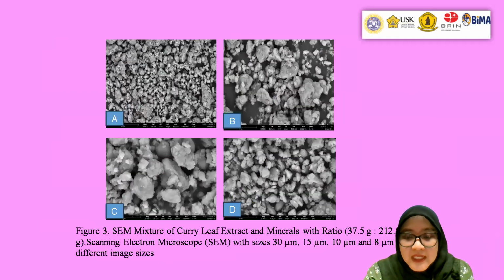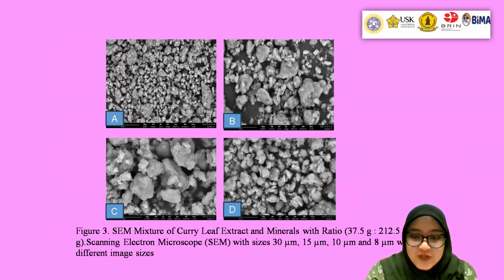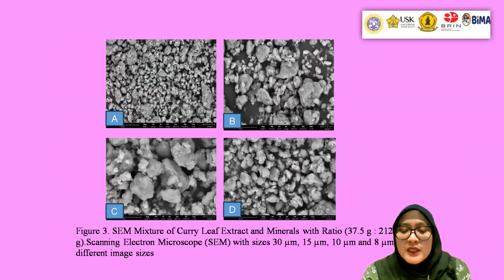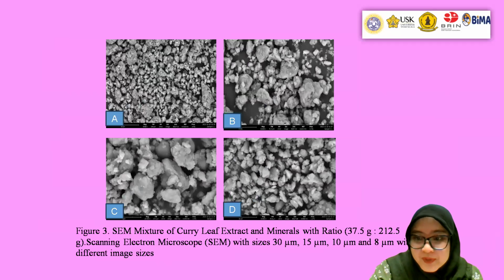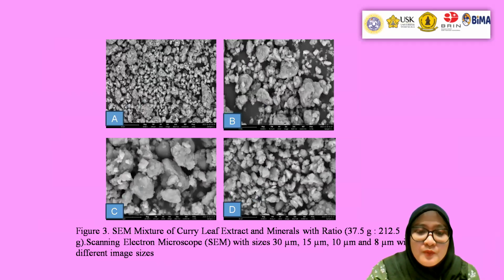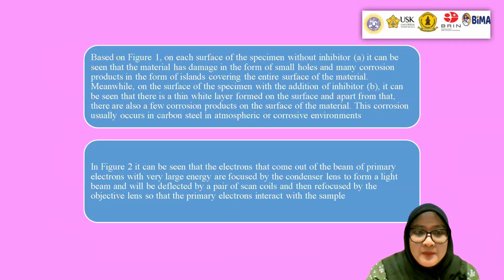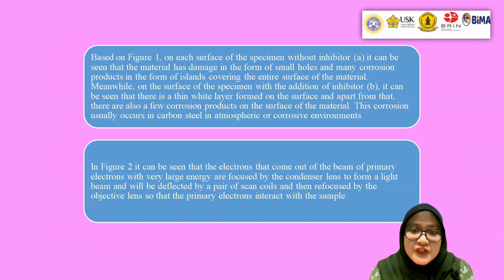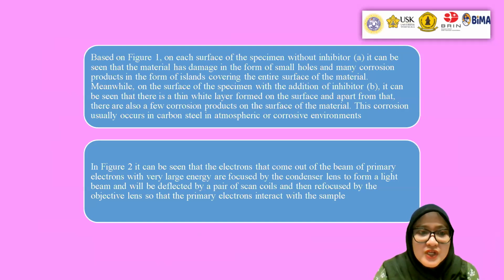And figure 3, some mixture of curry leaf extract and mineral with ratio 37.5 gram between 212.5 gram, and scanning electron microscope with 30, 15, 10, and 8 micrometer. And based on figure 1, on the surface of the specimen without inhibitor, it can be seen the material has damage in the form of small holes and many corrosion products in the form of islands